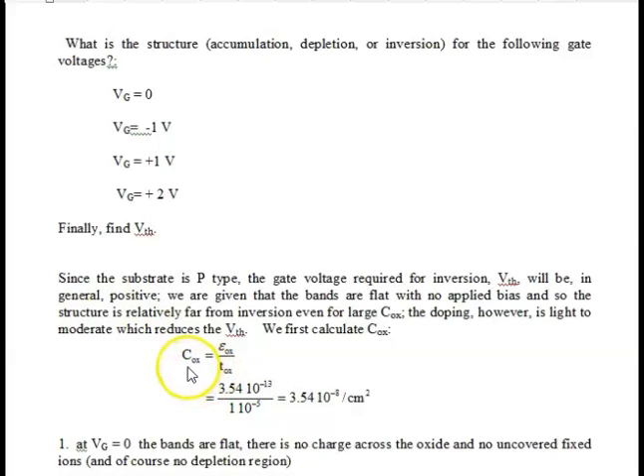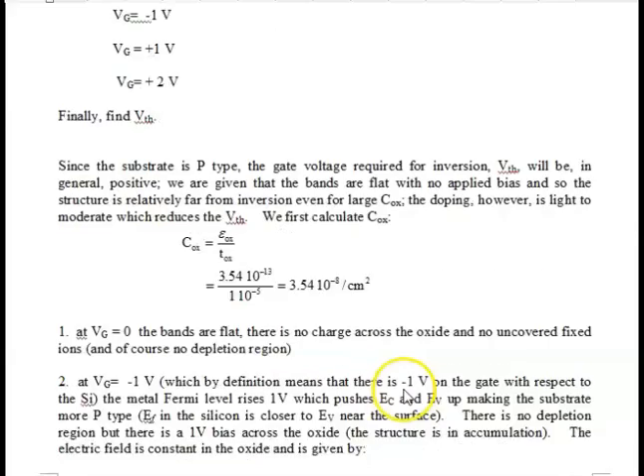gate oxide capacitance, C-ox, which is just equal to the permittivity divided by the oxide thickness. Again, this is the areal capacitance, so the units are farads per square centimeter, and the oxide permittivity is here, and the oxide thickness is 10 to the -5th, so we get a relatively small value for the gate oxide capacitance.